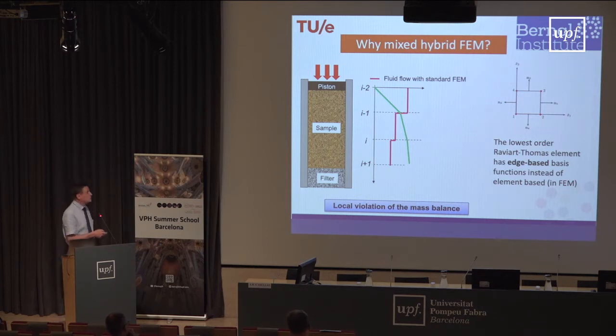Now you see immediately what the problem is: this element pushes out so much fluid, according to that red line, into the next element, and into the next element only less comes in. And same thing with the jump here across the elements, you have a discontinuity. So the flux out of one element is not equal to the next one. And this is not an issue as long as it is globally accounted for, with most finite element codes you can use Abaqus without any trouble. But when you go to very large deformations, you get really into trouble.